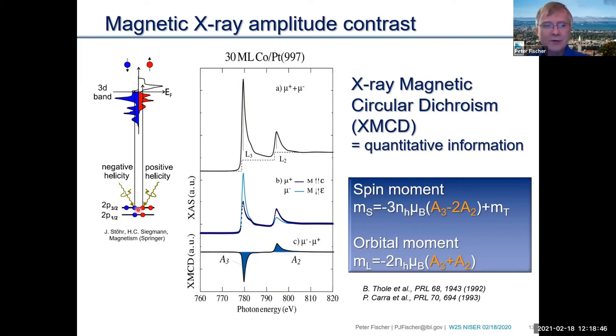And in a Kerr microscope, of course, you come in with polarized light, so that's the similarity. You come with polarized light onto magnetic materials, and then you reflect off or you do some transmission in Faraday, whatever. And then the magnetization actually changes slightly the incoming light. That means the outgoing light has a little rotation of the polarization, things like that. That means you modify the photons in the Kerr microscopy, in the Kerr effect. But you're basically having transitions that are right here.